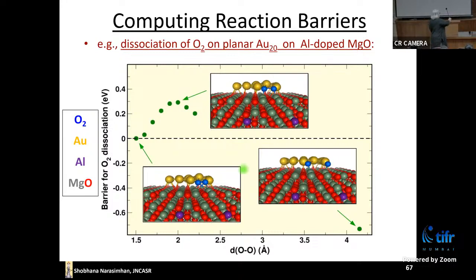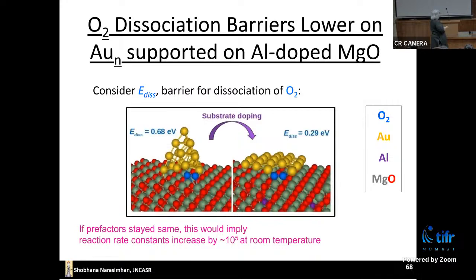And what these green dots here are showing you is how the energy changes when you do that. Okay? And we find that if you look at that energy, the energy it requires to dissociate it, when you have the undoped support and the clumped up nanoparticle, it's 0.68 eV. If you do this instead, it lowers significantly to 0.29 eV. So that means the reaction is much easier to take place.